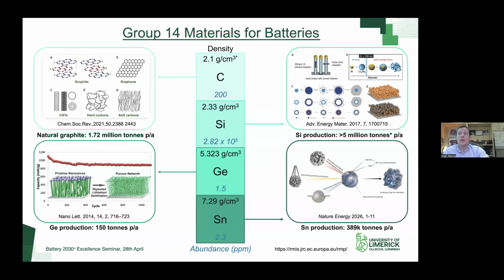Just to flag, I mentioned around the production discrepancies here. This is data taken from an EU website, which is really useful. It points out the production values for different materials and sources of them. For example, natural graphite is about 1.72 million tons per annum. Silicon is about 5 million tons, depending on the quality. So there are a range of different silicon qualities. Germanium globally is about 150 tons per annum. So you can see that the amount of germanium that is made, despite it being a really important material, for example, in fiber optic cables, is far more limited compared to tin, which is up around 389,000 tons. Okay, so we're talking about 3 orders of magnitude difference between germanium and tin.